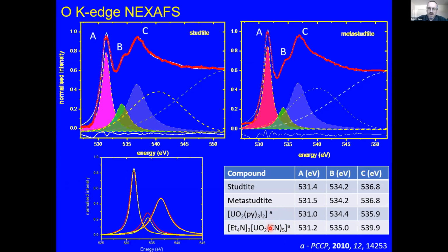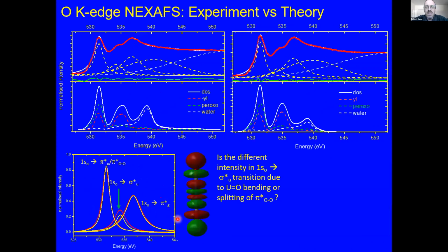We chose the cyano complex because this has anti-bonding CN molecular orbitals, which can get involved in the bonding to the uranyl as well. And we have exactly the same situation with our oxygens from the peroxy species. So looking at our MO diagram, we could assign this peak to the transition to the pi star U, this one to the sigma star U, and this one to our pi star G molecular orbitals. But we already have the theory to look at this. So does this fit with our theoretical ideas?